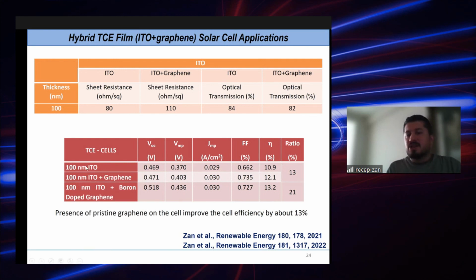I hope you can follow me here. The silicon cell with 100 nanometer ITO gave us 10.9% efficiency. But when we use ITO along with single layer pristine graphene, the efficiency went up to 12.1. And when we use ITO along with boron-doped graphene, in single layer or double layer at maximum, we obtained an efficiency of 13.2. The increase in comparison to the pristine one is quite nice, 13% or 21%. We fabricated many samples, 100 solar cells, and we never went below 10% at all, especially for pristine.